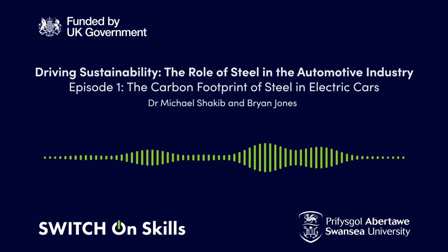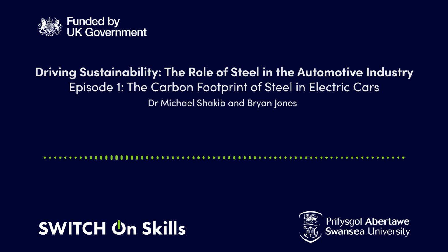Well, mild steel is typically 0.03 to 0.04% carbon after the basic oxygen steelmaking process. Higher strength levels can be achieved by additions of carbon in particular, because this is the major element which affects the strength of the steel. You've then got manganese, which is the second primary element present in a mild steel product, at 0.3 to 0.6% manganese, as the other main composition element in your steel product.